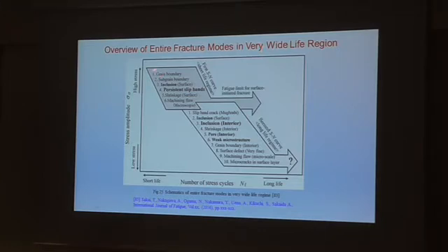However, there can be some other types of crack initiation, as I explained just before. And this is the second S-N curve. The interior inclusion induced fracture is the most predominant fracture mode in this second S-N curve. Okay? However, even in such a very long life region, we can have a lot of different types of crack initiation modes.